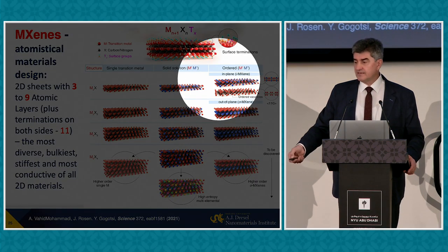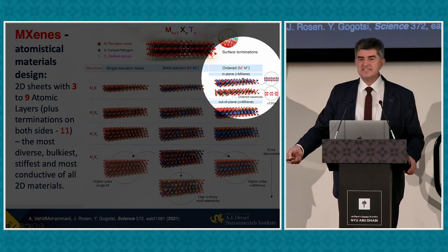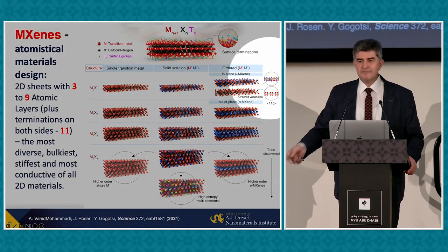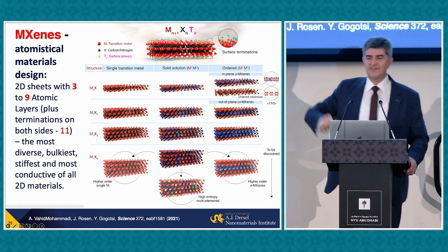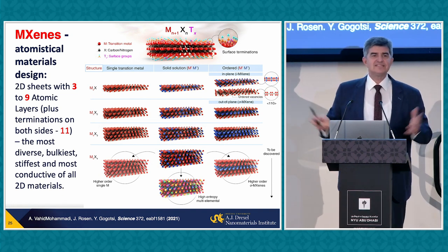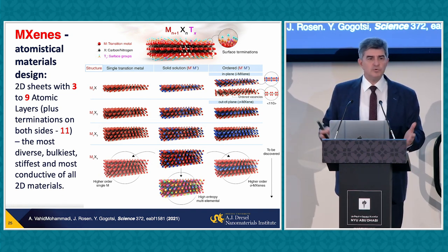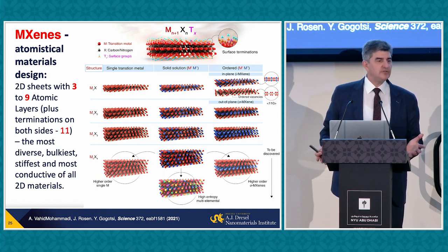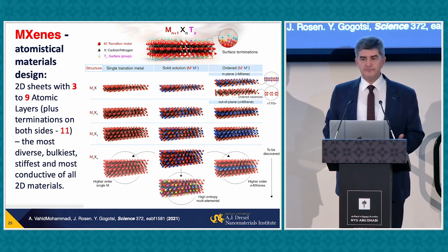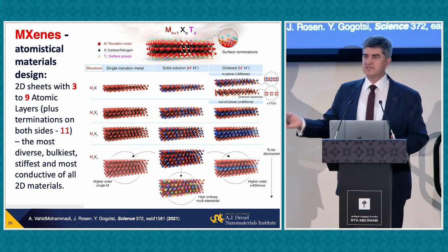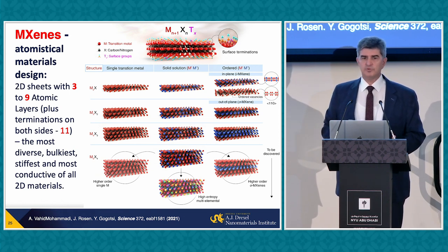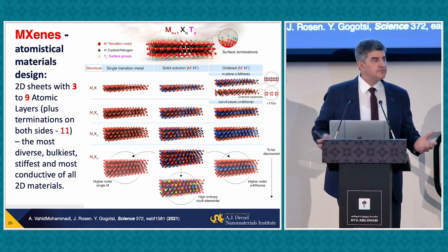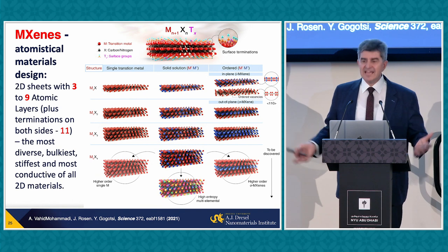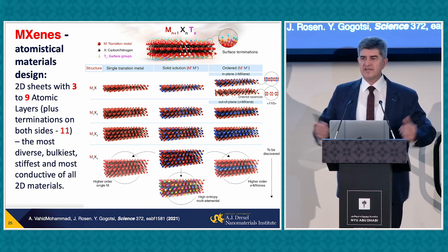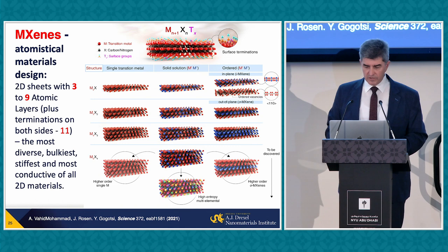Moreover, we can make materials with alternating atomic columns, or etch them away, making lines of missing atoms, vacancies. So basically, the sky is the limit. We can truly do atomistic design of materials. And if we have calculations, DFT, molecular dynamics simulations, telling us properties of materials as a function of composition and structure, we'll be able to design materials with virtually any set of possible properties because we have such a large space to work with here.